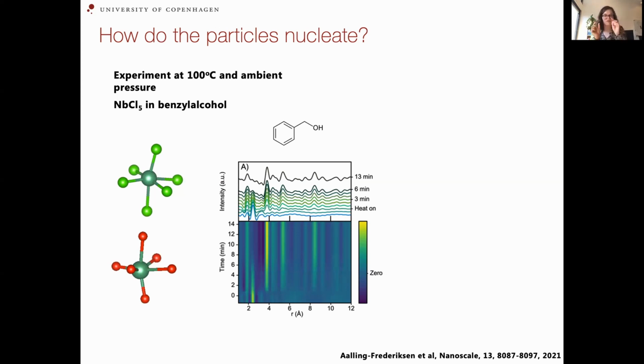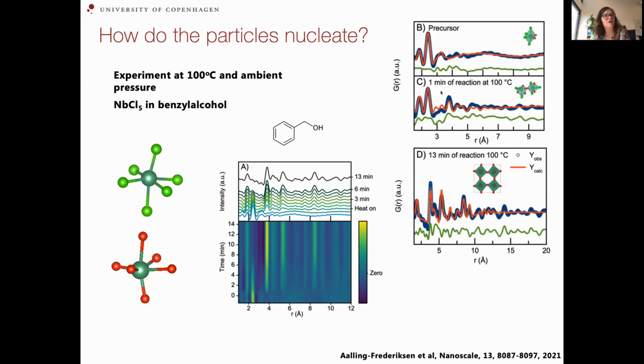And 2.3 angstrom corresponds perfectly to a distance between a niobium atom and a chloride ion in this precursor. But we also see a little peak here at 2.0 angstrom, and that corresponds to a niobium-oxygen distance. So what we could do is try to start making models for this, because the hypothesis for the reaction mechanism is that this oxygen will coordinate to the niobium, and then the chloride will act as a leaving group in the reaction. So we could start modeling these data with different sizes of clusters.